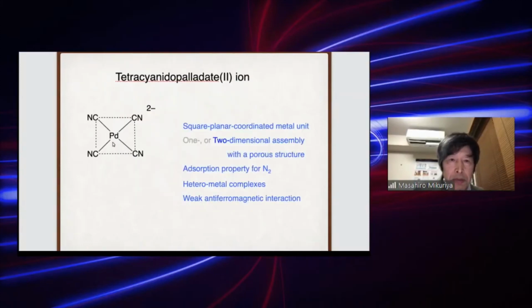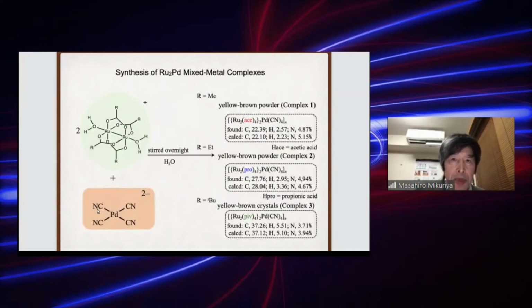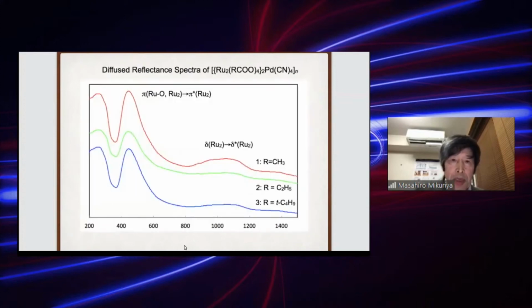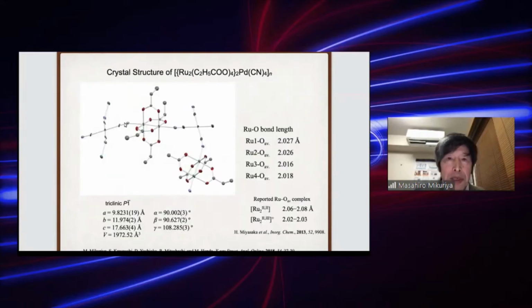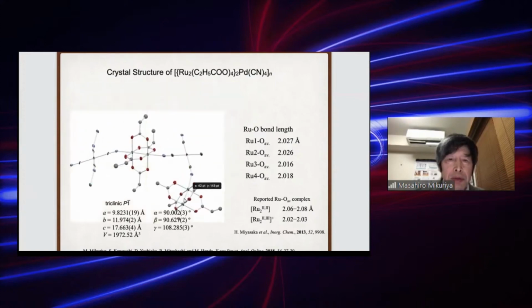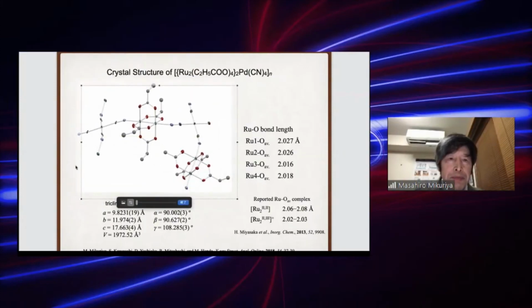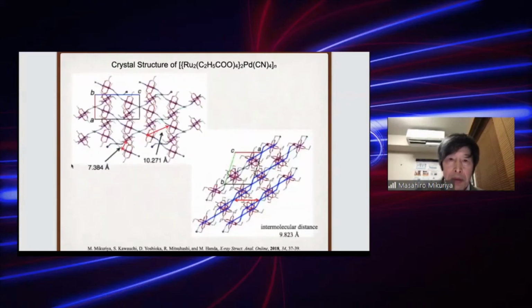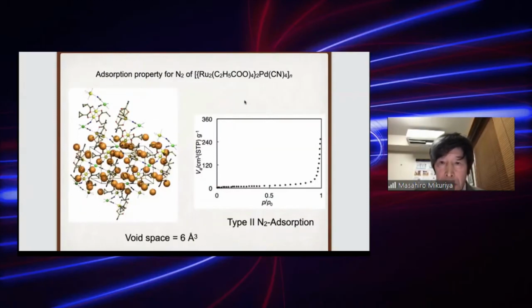And we used the palladium system by using tetracyanopalladate. We could obtain some assembled compound. And we could get the crystal structure of one compound in this series. And the dinuclear units are connected by tetracyanidopalladate to form assembly structure. And we can see some two-dimensional structure. And we measured adsorption property for nitrogen for this system.